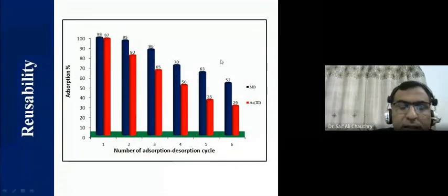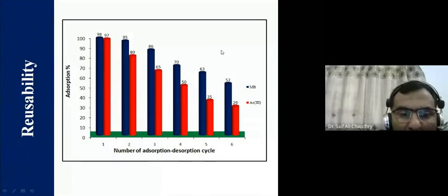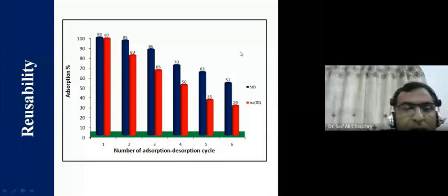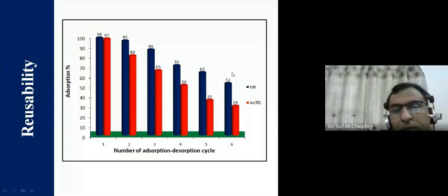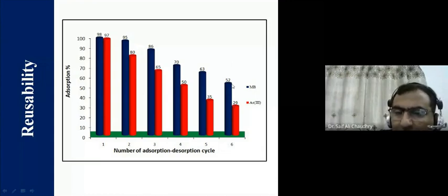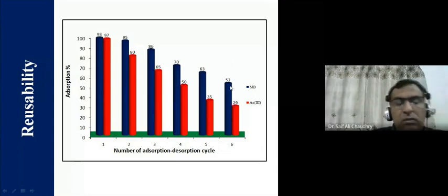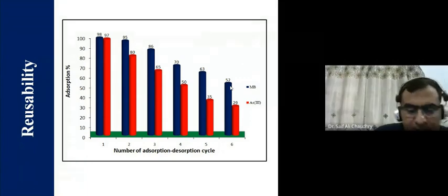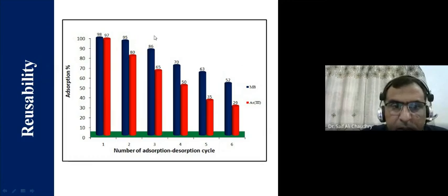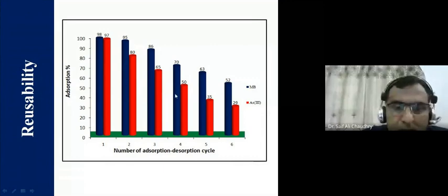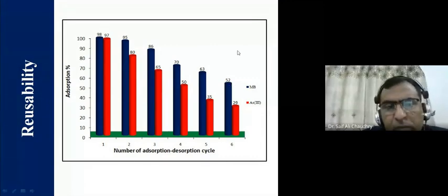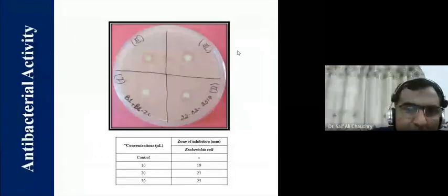Now the cyclic use of this material has been carried out, and these are the cycles: 1 cycle, 2 cycle, 3, 4, 5, and 6, up to 6 cycles. The adsorption capacity definitely got reduced for both arsenic and methylene blue. Methylene blue was the target dye we have used, but it still has sufficient adsorption capacity. Therefore, the material can be used in a cyclic way.